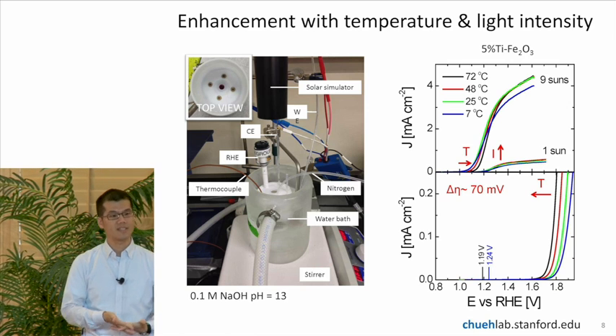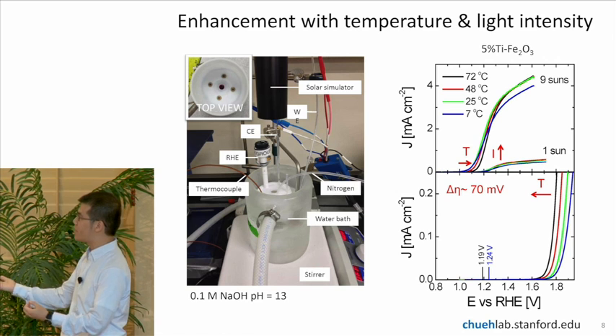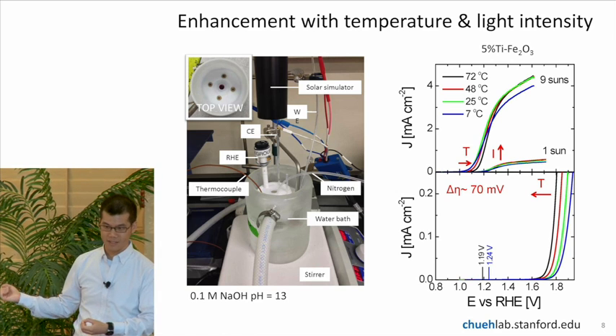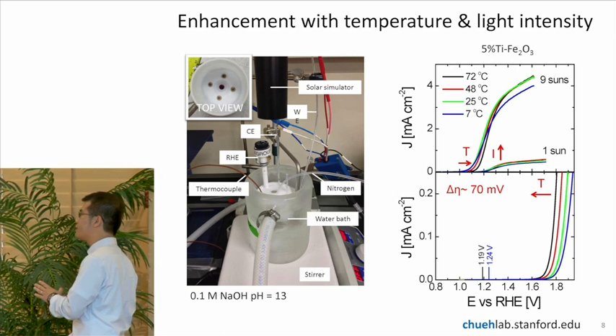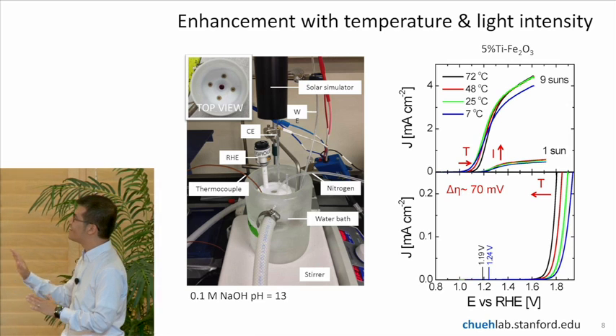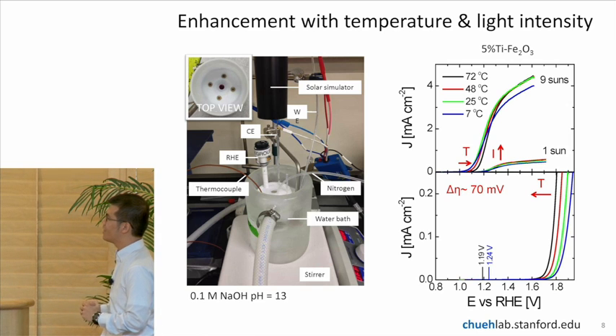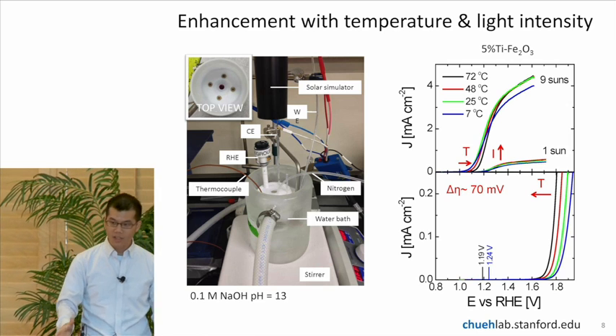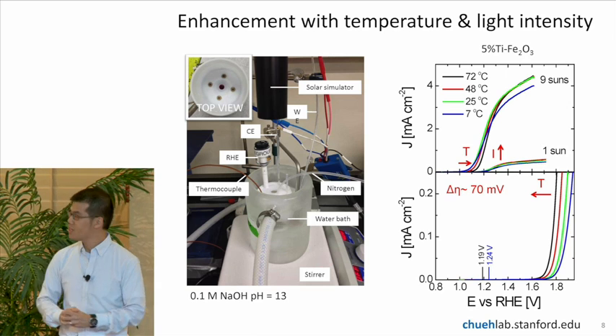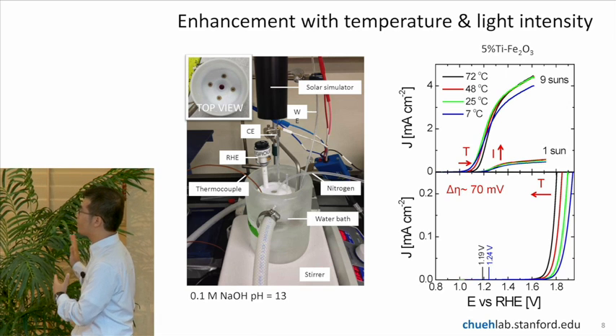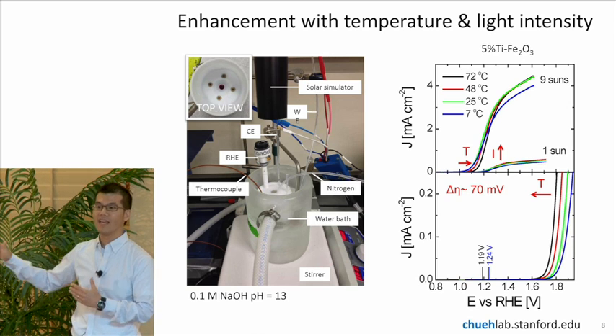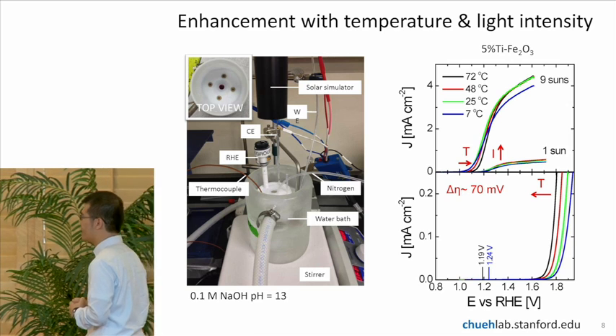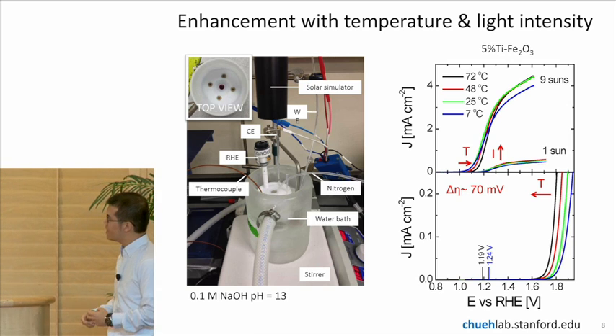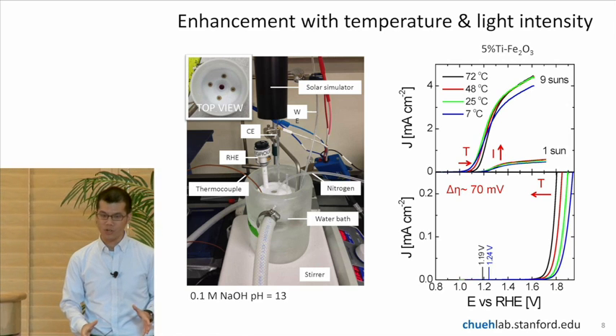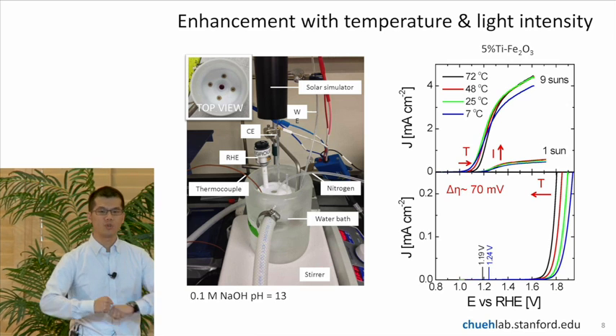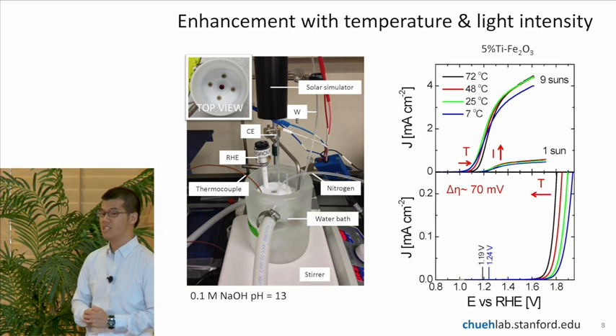Then when we increase the temperature, you can see the voltage actually moves slightly to the right. So as I mentioned before, we want the voltage to go to the left, so this is not the best situation. Now if you turn your attention to the dark current voltage curve, you see actually the curve is indeed shifting to the left if you don't have any light. And what's more important is that when you increase the temperature, the driving force needed to break the water molecule decreases as well.